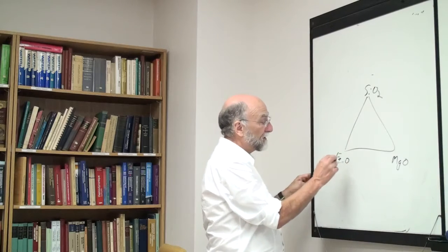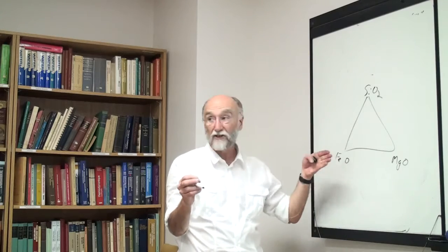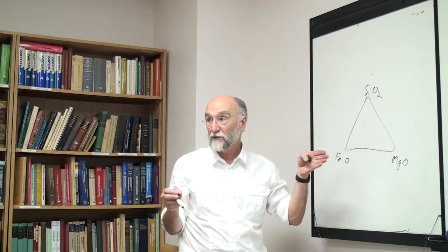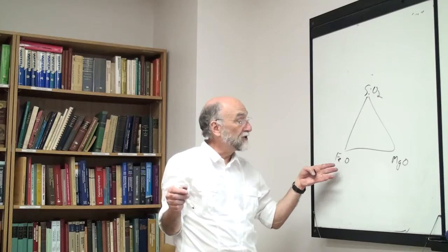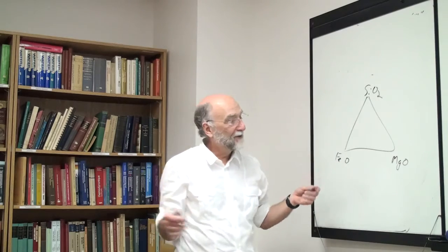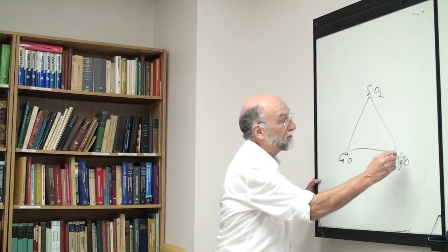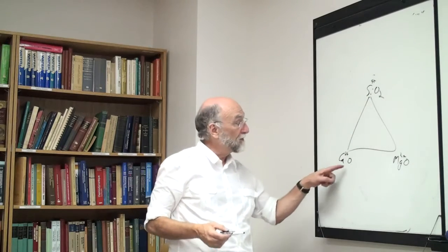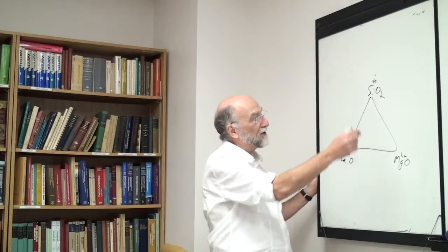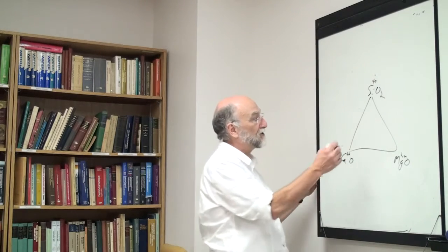But, well, one thing, I'll talk about that on Tuesday. If I have FeO here, now, this already is not a quasi-ternary section, because as you change the oxygen content, the 2+ and 3+ ratio can change, so that's not quasi. But if you have calcium oxide, well, you know the calcium is almost always 2+, magnesium 2+, silicon 4+, you don't deviate from the oxidation states. If you have something that has two oxidation states, though, like iron, then right away it's very unlikely you're going to hit it. But okay, even in this quasi-ternary system, there are some quasi-binary sections and some aren't.